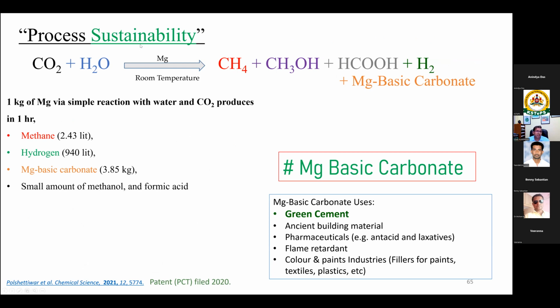So in order to show that, we calculated some sustainability metrics. 1 kg of magnesium produces 2.43 liters of methane, 940 liters of hydrogen, and 3.85 kg of magnesium basic carbonate. So even if methane or methanol is not my product, and magnesium basic carbonate is my real product, you're still converting CO2 into these, so they have their own value. Look at the magnesium basic carbonate: it's 3.85 kg from 1 kg of magnesium. And basic carbonate has lots of applications, it can be used in green cement, building material, pharmaceuticals, antacids that some of you may have taken, and other applications.